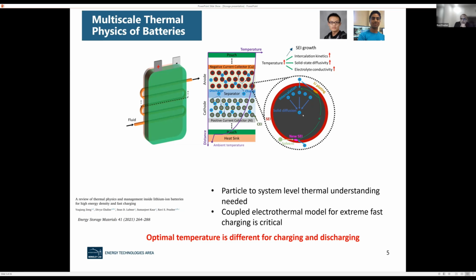So if you zoom in here, there's very interesting physics happening. You have solid state diffusion of lithium happening inside this, say, graphite anode. So lithium is diffusing in, right? That's happening. Then you have something called solid electrolyte interface growth right at the interface, which is not very desirable. And depending on how fast you're charging, lithium may not be able to diffuse inside, and it is plating, okay?